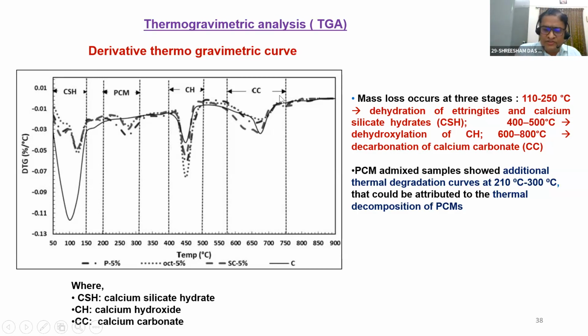So normally you get three peaks. But when you add PCM, now you can see the dotted line performing. One is my CSH, and in this temperature boundary of 200 to 300 degrees centigrade, I'm getting one additional peak. And my CH almost at a similar temperature, even the CC also at a similar temperature.